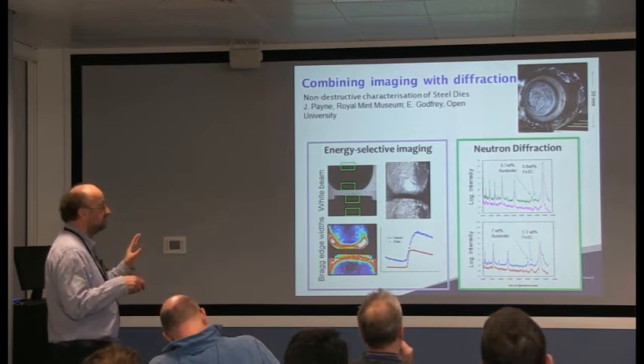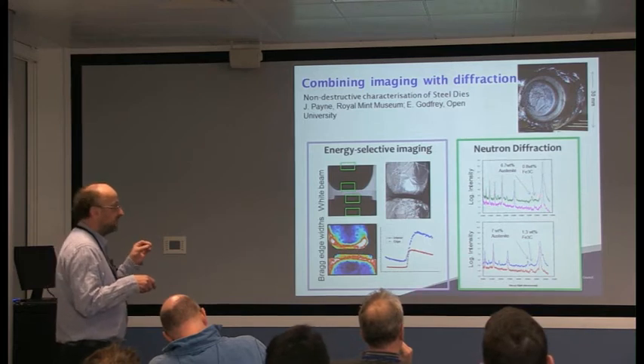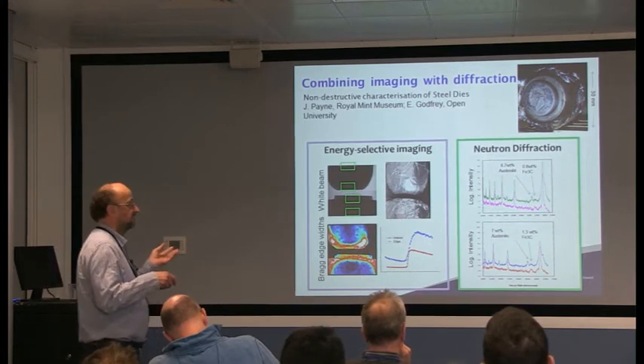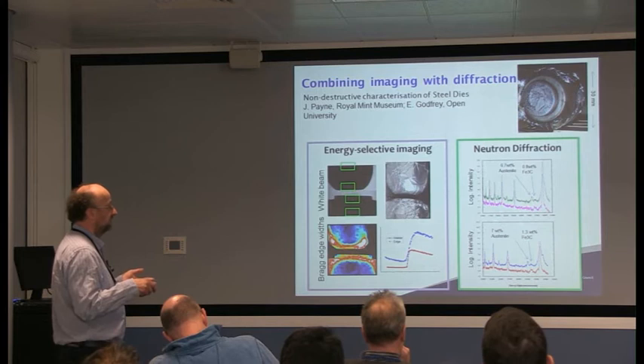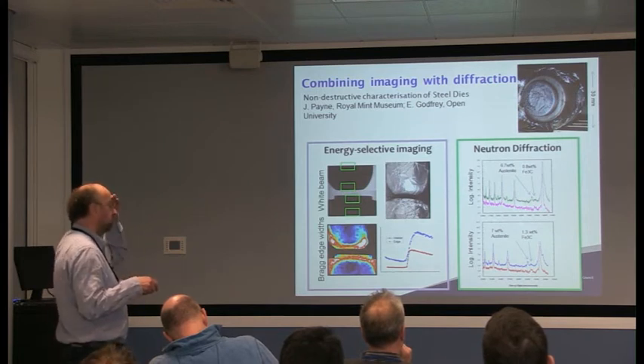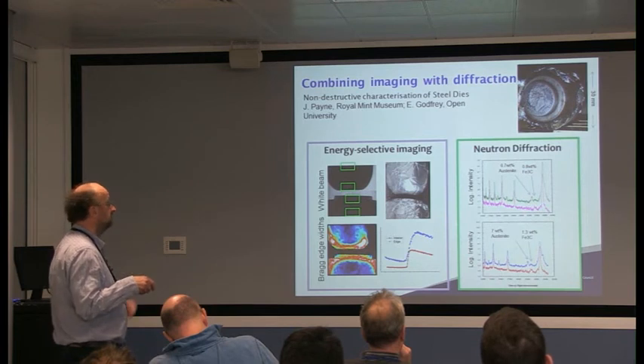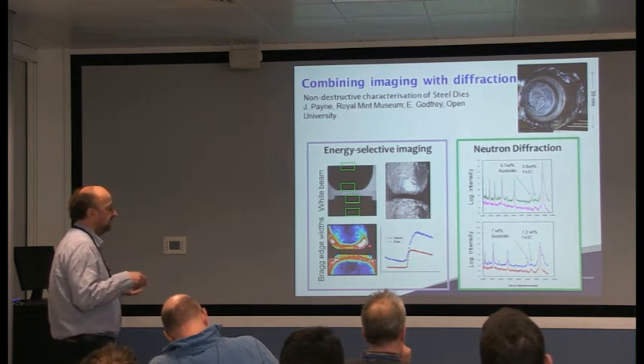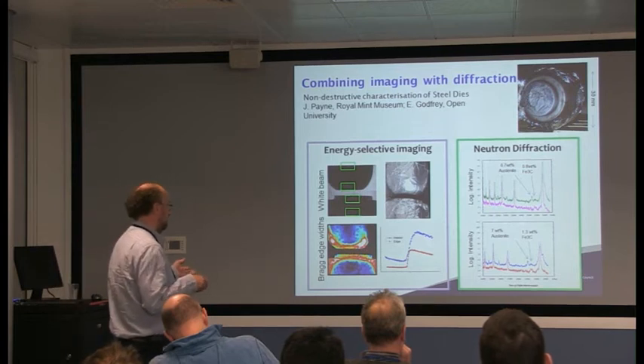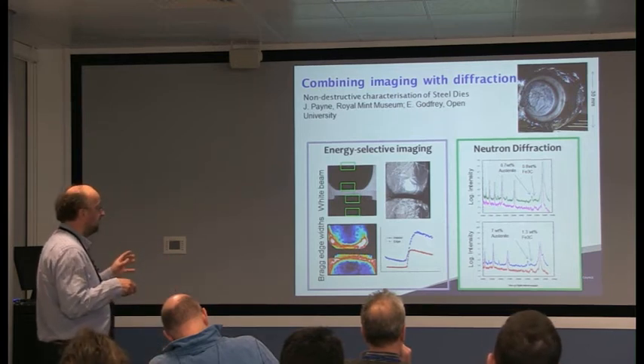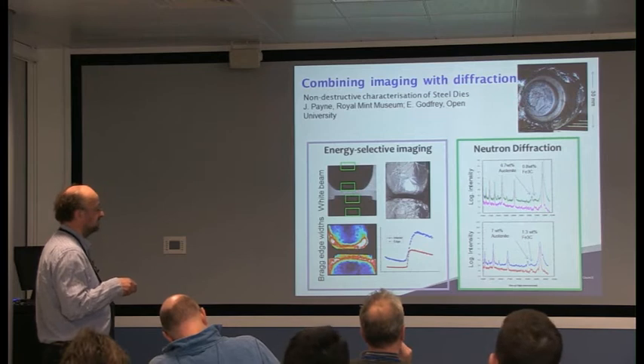We need the diffraction, where we measure with a lower spatial resolution, what we pick up just more subtle structural details. With a spatial resolution, let's say, of a millimeter or 2 millimeters, but we still need the imaging techniques to map the main parameters with a higher resolution.